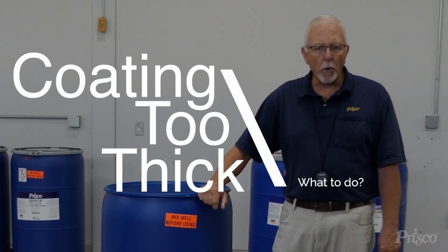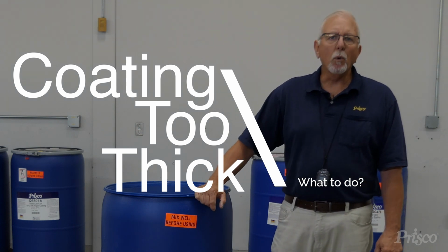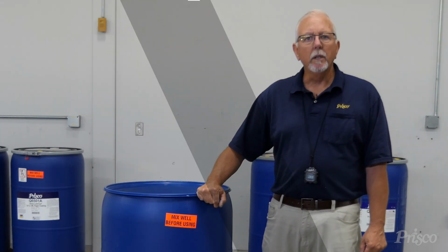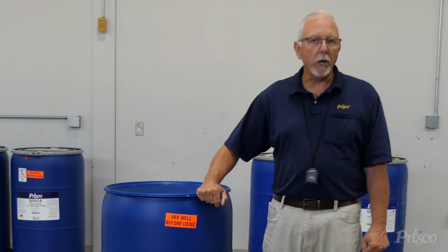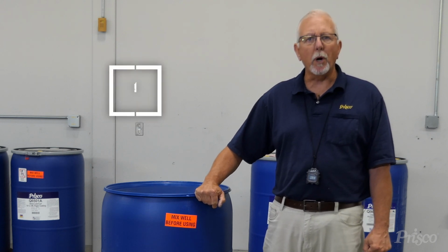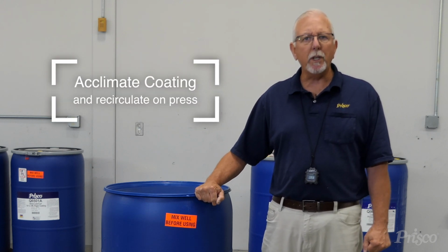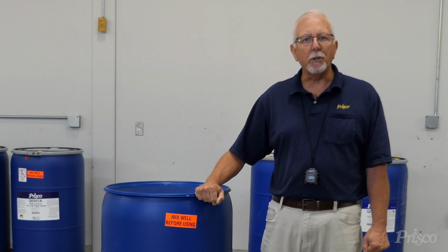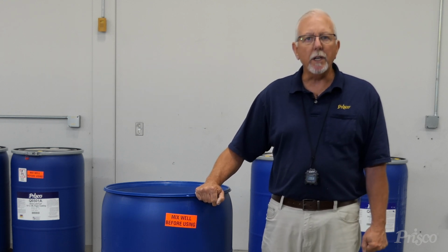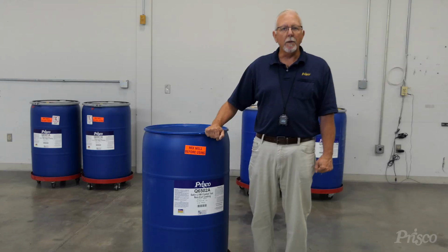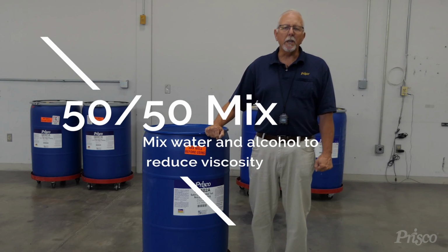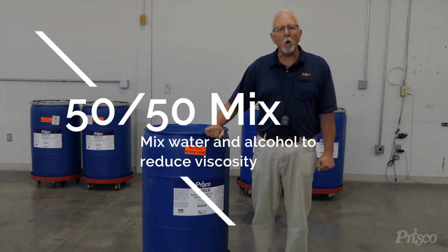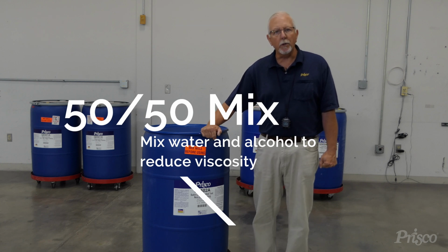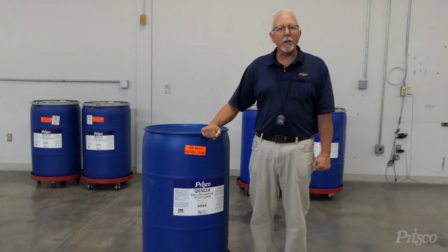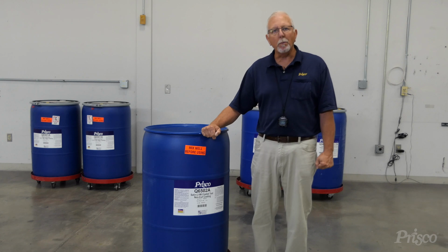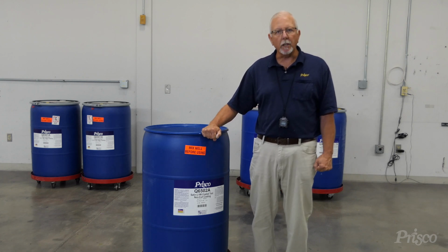So what do you do if the coating's too thick? Number one, you gotta make sure that the coating is at room temperature or press temperature. So make sure you put it on your press, let it recirculate for about 15 minutes until it gets to the proper temperature. Then go ahead and take a viscosity reading. If it's too thick, we recommend using a 50% water, 50% alcohol mix to reduce the coating. 1 gallon of that mixture will reduce a whole drum of coating 5 to 7 seconds.